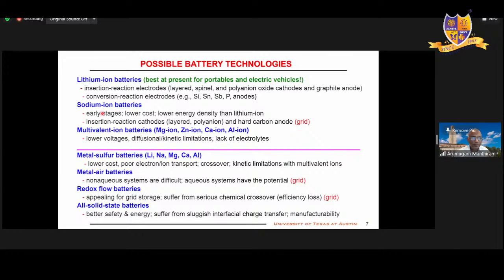All these are using mined metal ion cathodes, iron, cobalt, nickel, manganese. They have to be mined. So if you use sulfur as a cathode, then you do not need any manganese, cobalt, nickel, nothing. And that can be coupled with any of these, lithium or sodium or magnesium working ions.